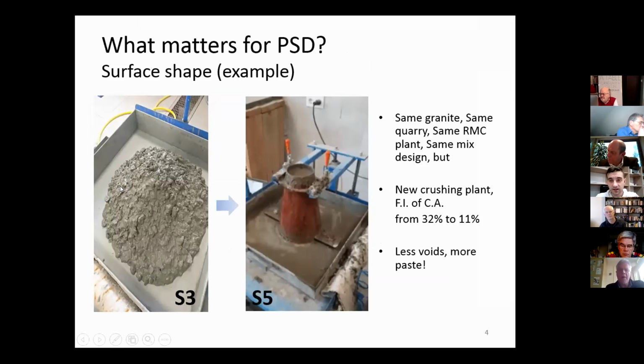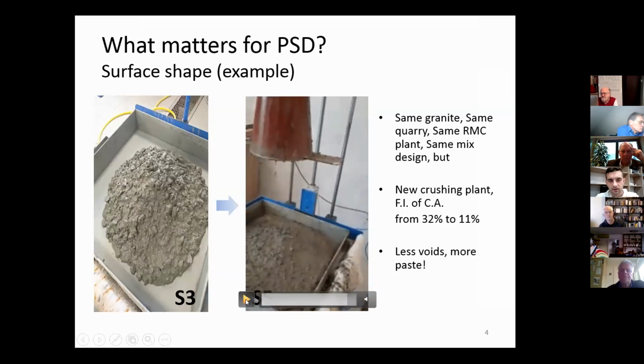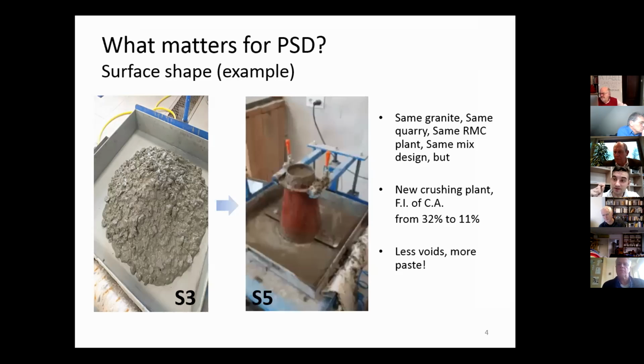There is one ready mix plant which is supplied by one quarry. They erected a new crushing line, and the old one you see on the left is with the old material with flakiness index 31%, 32, sorry. And on the right side, you can see, look on the video. So this is a totally different concrete with just changing the flakiness index from 32% to 11%. We were also very surprised that with the same formulation, same mineral, same RMC plant, everything is the same, just flakiness index moved, we have this kind of result. We have less voids, we have more paste, concrete is more flowable, more creamy, and this means that the grading was completely the same.